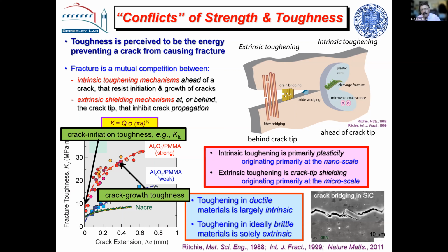Well, in the fracture world, it's that rising R curve that gives you that. It's basically a parachute. Effectively, instead of just breaking when the crack initiates, you allow the crack to grow stably and generate toughness. So you'll see this in all these materials. We're trying to develop an R curve. Now, the fracture mechanics of the R curve, a little bit more complicated, not quite as robust as crack initiation, but from the perspective of alloy design, it's absolutely critical.